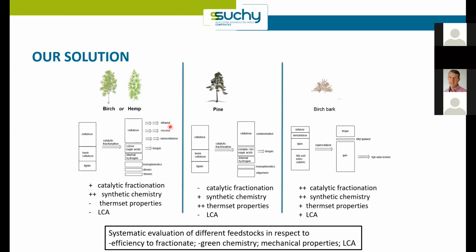So to make a long story short, what we did was we chose a few different feedstocks. First we chose birch and pine, but then we also added the hemp hurd, and the hemp hurd is the piece of the hemp that does not go to fiber, and it looks like wood more or less, and also birch bark. And then we systematically evaluated these feedstocks for generating both the monomer, but also in terms of mass balance, we don't generate a lot of waste, as I showed on the previous slide. So that means that we have to evaluate the fractionation, and then also how well the monophenolic compound that we get out performs as a polymer. And then also, of course, the chemistry to produce this.